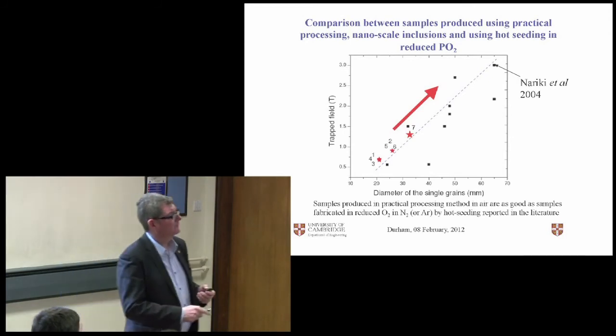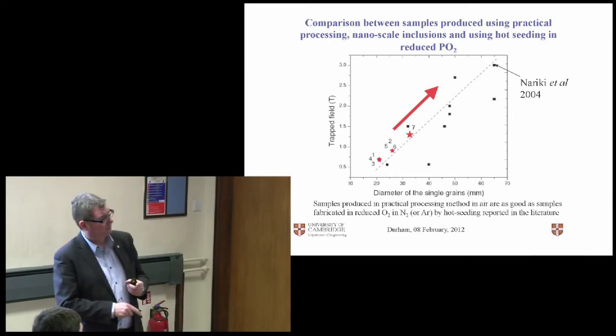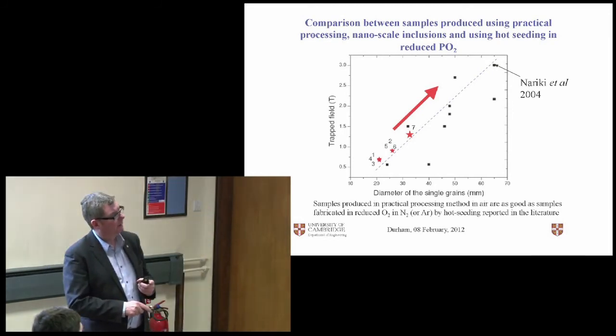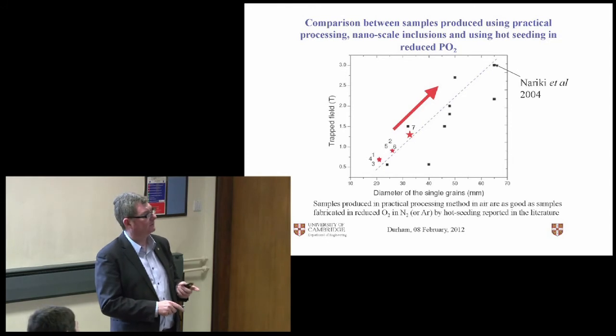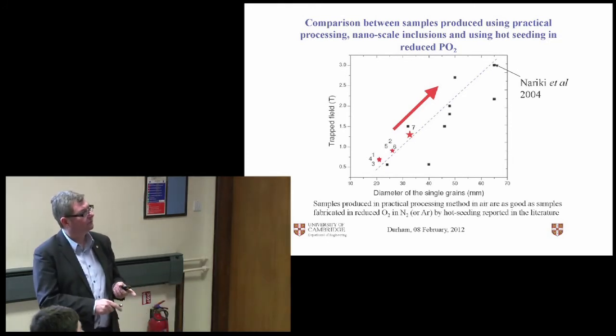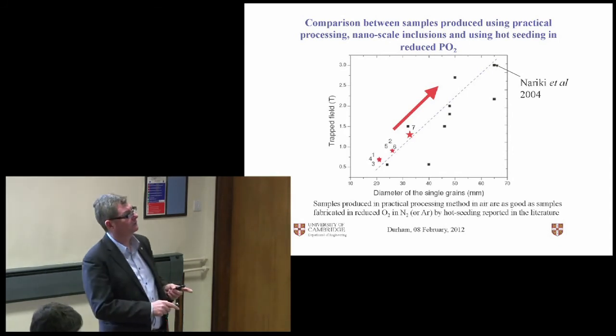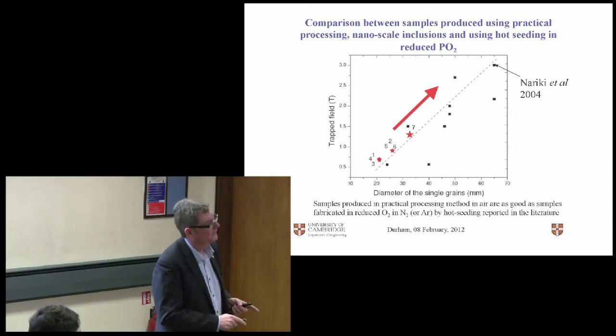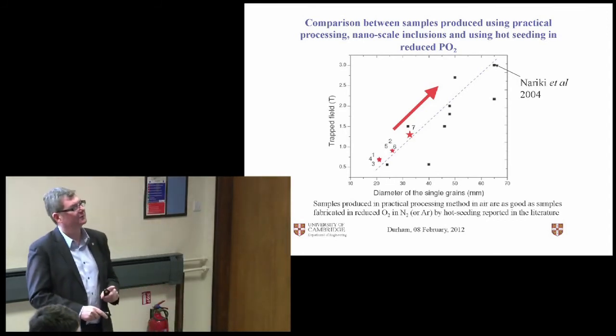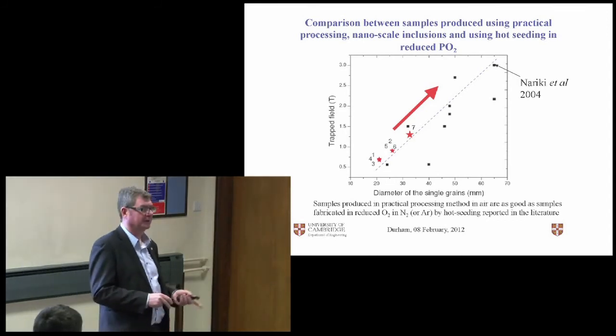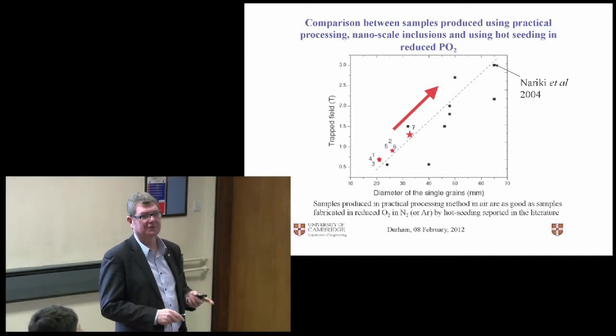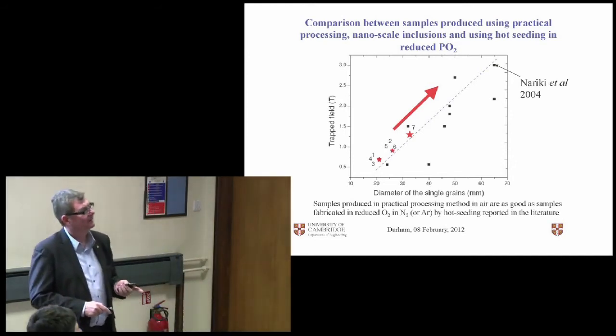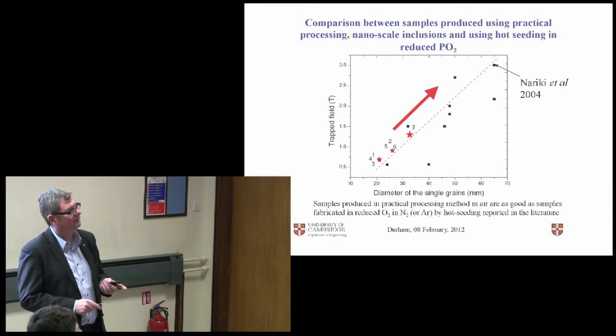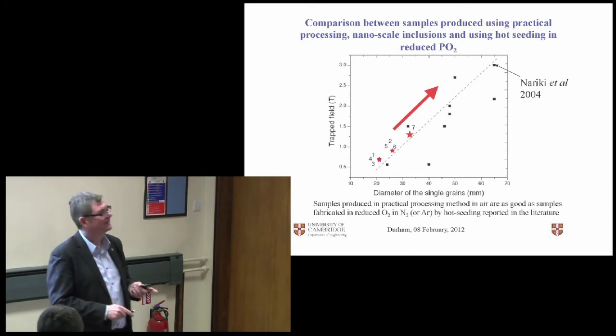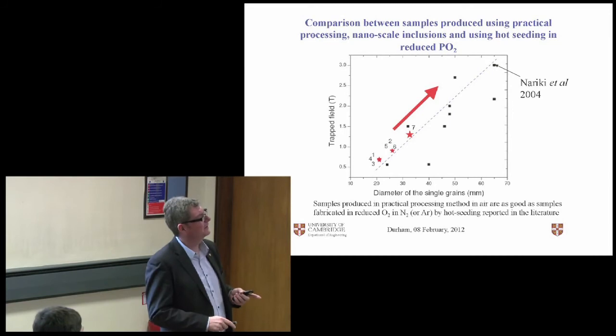Okay, so if we started constructing this plot, it's trap field versus diameter of single grain. The red stars on here are our samples, everything else is other people's. And the other people's samples have all been processed using either hot seeding or reduced oxygen partial pressure. And I really like this plot. For undergraduates, I say, whenever you put a plot up like this, be careful where you draw your straight line, because you can draw it anywhere. In my case, it was very convenient to draw it here because all our results are slightly above it. But you could argue there could be a different straight line there.